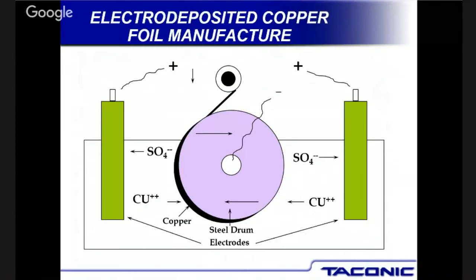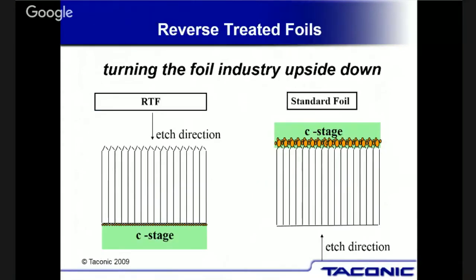But what it also does, and I'll switch this one. I call this one here on the right-hand side standard foil. When you're etching standard foil, this is the tooth on the top. You can see where it says C stage. There's the tooth, and you're etching it from this direction. And this is the drum side. And the drum side is like a skin, is the best way to put it. And so when they're etching through that skin, it doesn't etch uniformly. And so what you end up having is a trace that doesn't look rectangular. It basically looks like a trapezoid or like an hourglass.